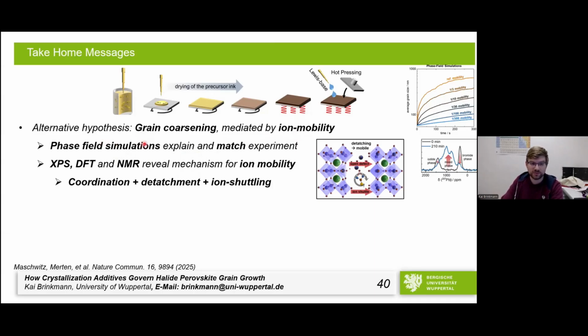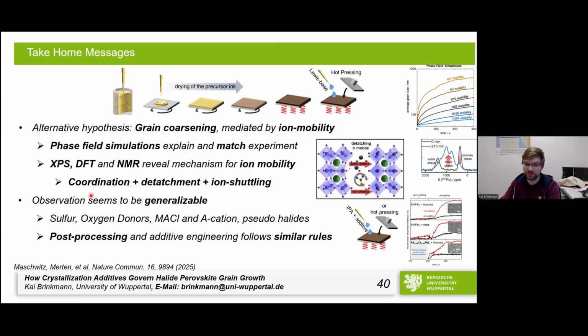We did phase field simulations, they matched. We did XPS, DFT, NMR, everything matched together. So we are actually quite sure that eventually ion mobility is what makes our grains big. And as far as we could see, it seems to be pretty generalizable.